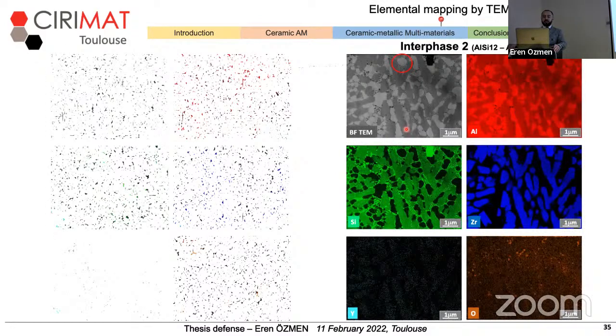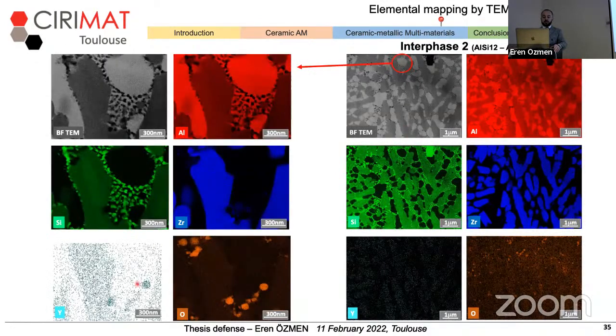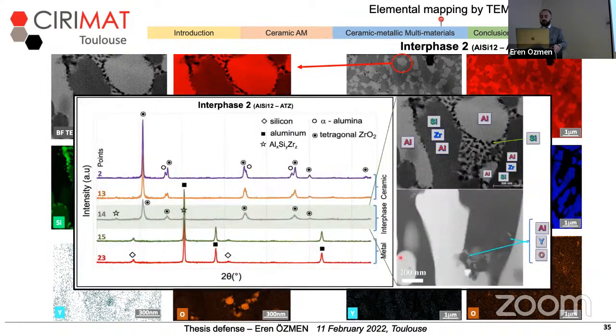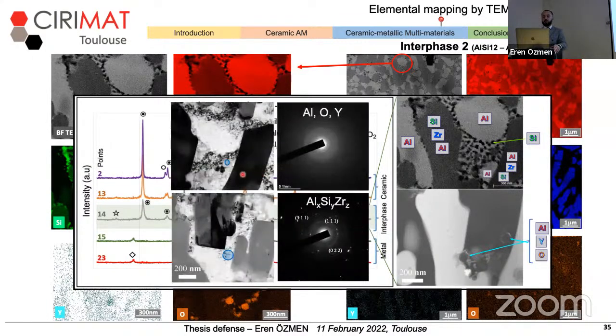So for the second interface, if we come back there, we again see some yttrium concentrated dot-shaped areas. And when I study them again, as we show here, aluminum, yttrium, and oxygen-rich areas, we again cannot see them in microdiffraction measurement. And there again, when we compare the aluminum, oxygen, yttrium-rich areas with the areas where the ternary phase appears, while the ternary phase is giving diffraction patterns, the yttrium-rich areas are not giving any diffraction patterns because they are amorphous again.